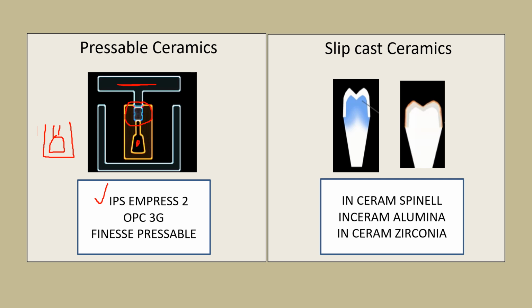Coming to the slip cast ceramics, this technique involves the condensation of aqueous porcelain slip over the refractory dye material. This dye absorbs water from the slip through capillary action, resulting in the formation of microporosity. And then this is fired at a temperature of 1120 degrees for 10 hours to obtain an opaque porous core. Later, the lanthanum powder is added in thin sections and is fired at 1100 degrees centigrade for 4 hours, during which the lanthanum glass infiltrates the opaque porous core and the strength of the core is increased by 20 times, over which a layer of ceramic is veneered. The examples are Inceram Spinel, Inceram Alumina and Inceram Zirconia.